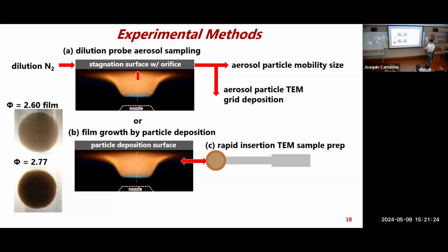What we'll see is that the particles observed under the microscope are different in each of these cases. It's not the perfectly same reproducible structure, there's a wide variety. But if you collect a particle from a diluted flow downstream, it'll look more amorphous. If you look at it here, we get a lot of crystal artifacts, and you get more soot. By having these deposition processes over time, I'm thinking there are some CVD-type growth processes that are not flame processes. So the way you sample this flame makes a difference in the products you're observing.